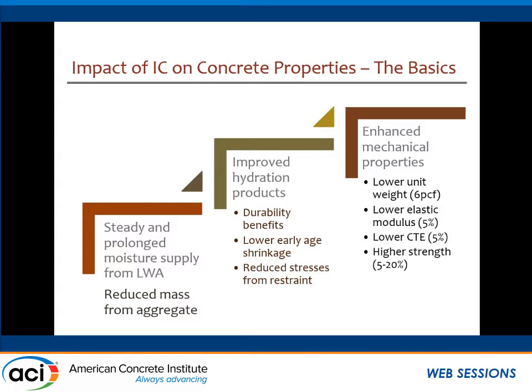Now, this is a summary, sort of an average observation from several studies that we reviewed. On average, you're reducing the unit weight by about 6 pounds per cubic foot, but you're also reducing the elastic modulus by about 5%. You're lowering the coefficient of thermal expansion by about 5%, and you're improving compressive strength anywhere from 5 to 20%, is what we have seen. That's the range in the data that we've reviewed in various references.